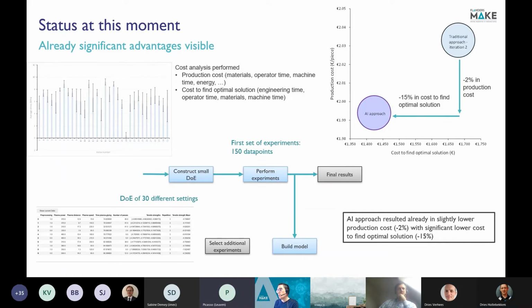And what we see up to now, even though we didn't complete the cycle yet, is that we already saw a significant advantage by using the AI approach. So we compared the approach that Ivo explained before with a traditional approach where we use the contact angle measurements. And what we see is that we can achieve a 2% reduction in production cost already with 15% lower cost to find the optimal solution. So this indicates that this AI approach can show significant advantages. And we hope, of course, that we can reduce this production cost even further, while we still keep into account that the cost to find the optimal solution will not be too large.